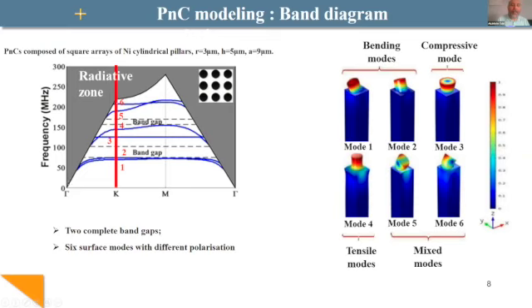The delimitation between the two zones is defined by the low velocity mode present in the structure. In our case, this is the Rayleigh wave, the small velocity present in the substrate. But it can also be, for example, a shear transverse bulk wave that can delimit the bulk wave and surface wave.